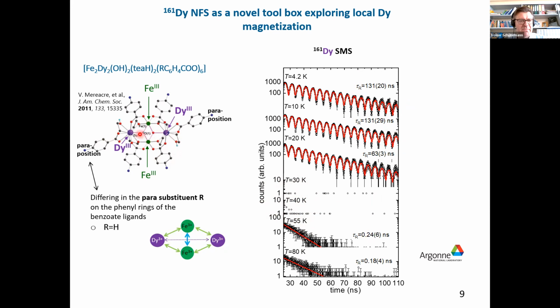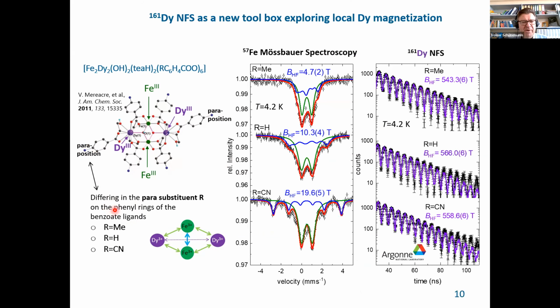I should mention, this is a complicated molecule, but the chemists can even manipulate the positions far out of the metal centers here. So this one had at this para position a hydrogen, and they could manipulate this position here by, as I said, a hydrogen or a methyl or a cyano group. And they did that before we started our investigations. And these 3 molecules have different Mössbauer spectra at 4.2 K, namely a doublet here and a magnetic sextet, which is a function of the modification at the para position.